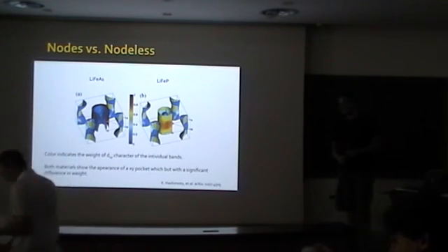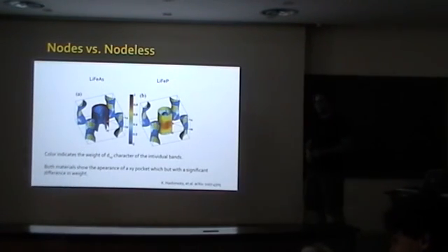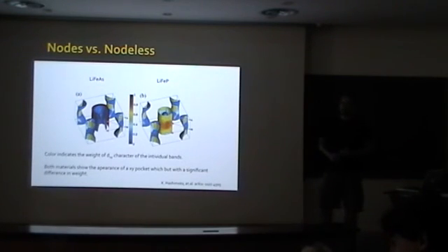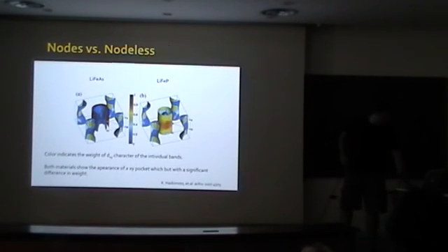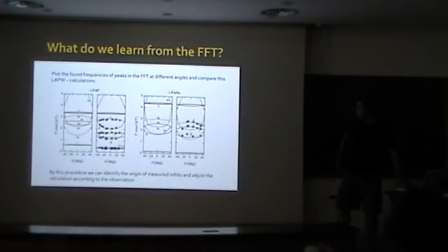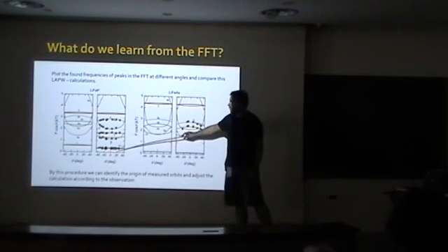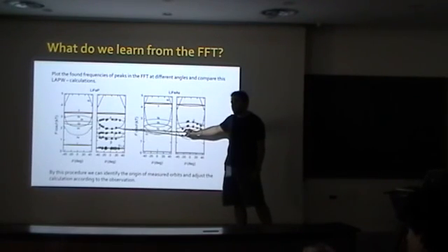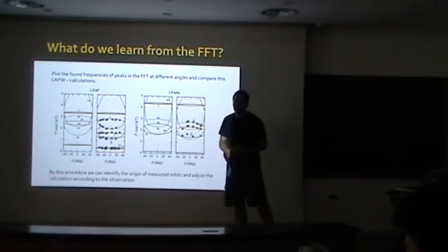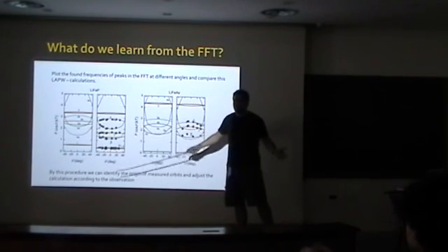Yeah. Maybe 2 questions. One is when you shift the bands compared to calculation. In principle, that can change the number of carriers, which means that you have to shift electron and hole bands in the opposite direction. Yes. So if we shift those bands, we're very careful that we compare the volume of electrons and holes before we shift the bands and afterwards, and make sure that the Luttinger count, so that the electron count, is correct before and after, so that this is in the same range, so that we do not generate hole doping or electron doping.